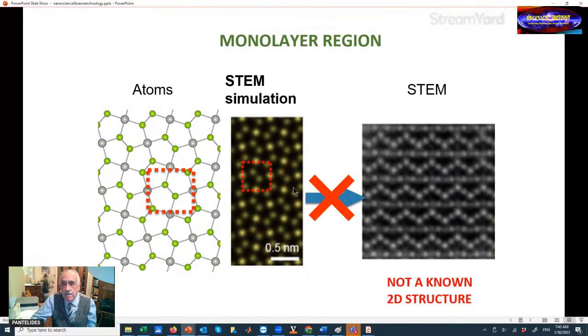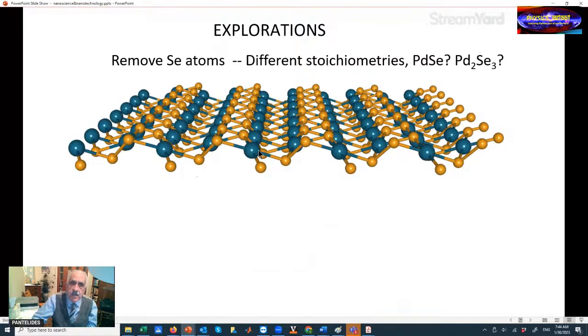The monolayer had a completely different image, like this. And if you look at the material, what it should be, the STEM simulation said that the image should look like this, which it does not. So this was not a known structure, and we used calculations using quantum mechanics, and we tried with the monolayer to remove a bunch of selenium atoms, which is believed that the electron beam can knock out selenium atoms, preferentially over palladium atoms. And we couldn't find anything that would match the image.